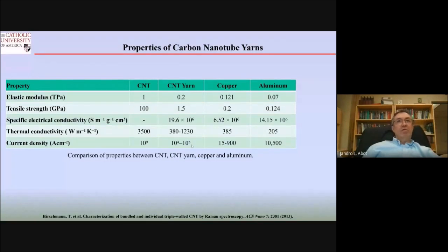So you would say, okay, why nanotubes? Why work with that? If we have copper, if we have aluminum, well, the idea is that you have a very light material, very stiff, very conductive, both thermally and electrically. It's also super light, and it has a lot of porosity as well. If you compare specific thermal conductivity or specific electrical conductivity to copper and aluminum, CNT fibers will beat them. CNTs will be better, but remember, with CNTs we're talking about nanometer level. I didn't mention, the diameter is about 9 to 12 nanometers.